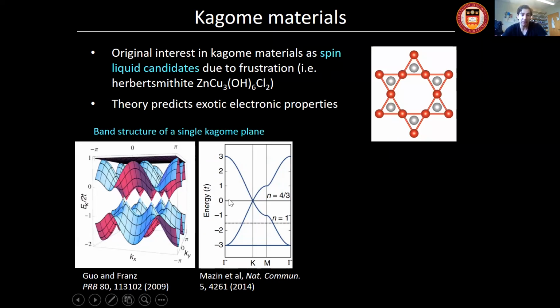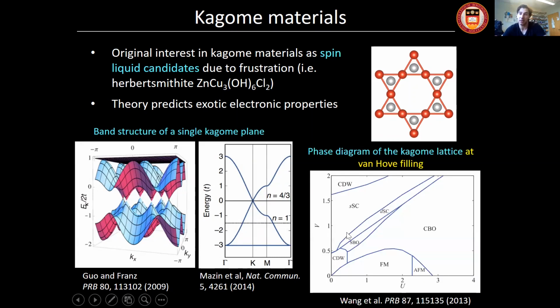One of the beautiful derivations of a single Kagome plane is the derivation of its band structure. If you look at an isolated Kagome plane and see what its electronic band structure is going to be, you can see that you will have these Dirac crossings at the corners of the Brillouin zone. And then there's going to be a Van Hove singularity above and below that, as well as a flat band that can emerge simply based on the geometry of the lattice. There's been a lot of interest in these flat bands, because if you tune the chemical potential exactly right, you can get a lot of interesting phenomena. So there's been a lot of interest in realizing this in real materials.